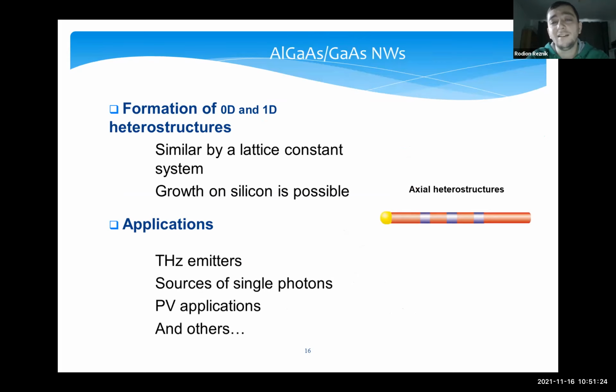So now I want to talk about a perspective material system as well: aluminium gallium arsenide for nanowires with quantum dots. The most important property of this system is that gallium arsenide and aluminium gallium arsenide have the same lattice constant. So there is no stress between the nanowire and quantum dot. So we hoped that that can lead to really high crystal quality and a sharp interface between nanowire and quantum dot.